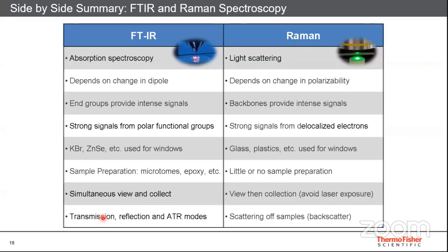End groups, for example in a polymeric chain, like a cyano group or a CHO group, show an intense signal in FTIR, while the backbone, like the CH arrangement, shows an intense signal in Raman. FTIR gives strong signals for polar functional groups, Raman for delocalized electrons. In FTIR, you have to use non-IR-absorbing windows like KBr or zinc selenide, while in Raman you can use glass and plastic as well.